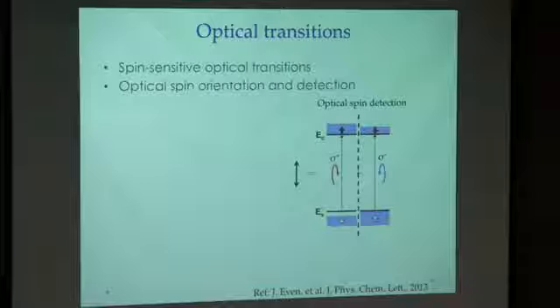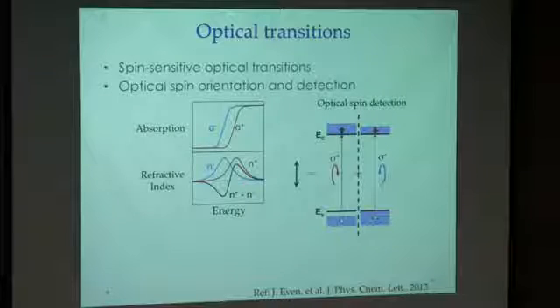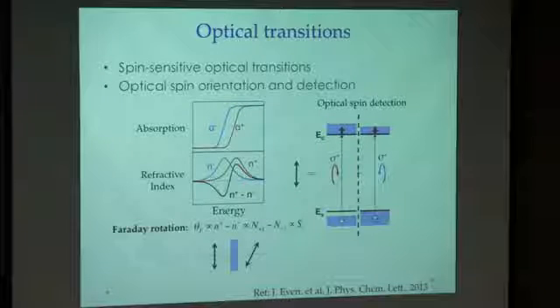We can measure that with a linearly polarized light, which can be thought of as an equal combination of right and left circularly polarized components. Because of that population difference in the conduction and valence band, the absorption edges for the right and the left circularly polarized light are a little bit different. This corresponds to that energy here, and this is a lower energy for the left circularly polarized light. Accordingly, you also have a difference in the indices of refraction for those two, and Faraday rotation measures exactly that difference in the indices of refraction.